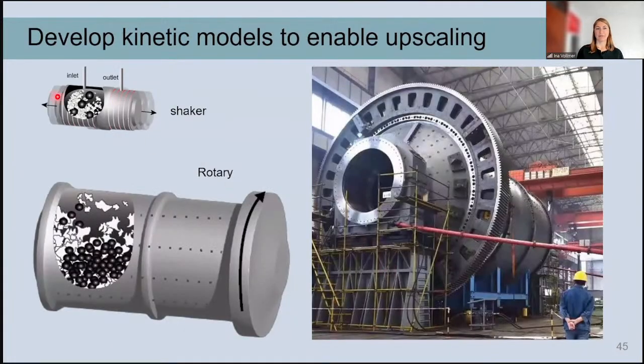However, we are working on a gram and sometimes even milligram scale, and we have this shaker geometry. And there are a lot of studies where it was tried to scale up these technologies and also move to other ball mill geometries, and it was found that this is very difficult. But a rotary system would actually be quite preferred, because there's quite some experience in the cement industry, for example, where they use these man-high ball mills. So it would be nice to know how we can translate this system to this large-scale system.